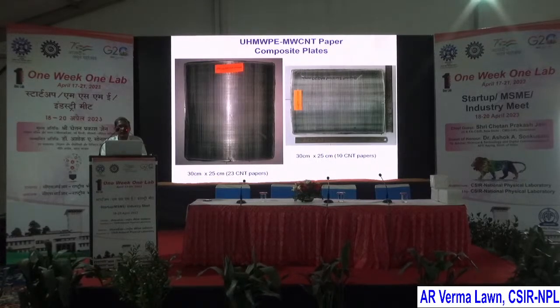Another application of this carbon nanotube bucky paper is in ballistic applications. Ballistic protection is very important for our soldiers and police force to protect them from any type of threat. This is the vest plate, which weighs more than 2 kg. It is made from ultra high molecular weight polyethylene fabrics, as well as another plate made from ceramics, that is boron carbide, sometimes aluminum oxide. So how can you reduce the weight of this vest plate? If you can reduce the weight by a minimum of 100 grams, from 2000 grams to 1900 grams, it also reduces the impact on the soldier using this type of material. NPL has developed some technology utilizing carbon nanotube paper to reduce some of the weight of this ballistic plate.